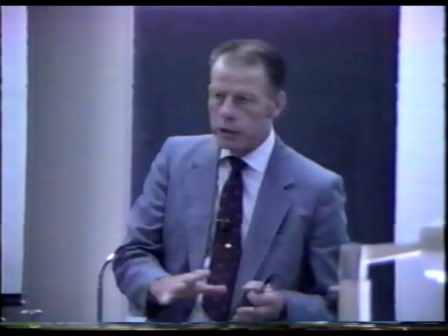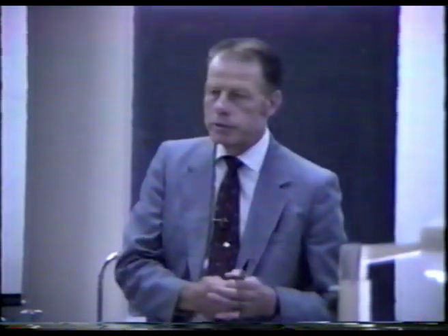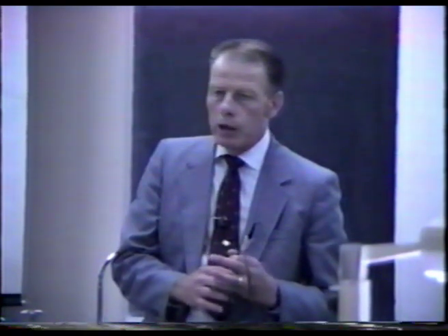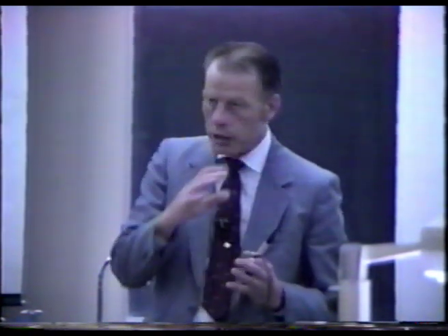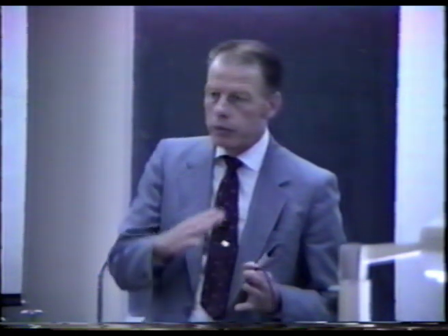You say, well, you start with 16 milliliters and go down to 10, and then you add another 6 milliliters to it. That's a drastic change in the concentration. And if you're depending on a surface species, that could greatly change the surface. That could be one reason, that it's a surface reaction, and you do something to the surface when you add the D2O.